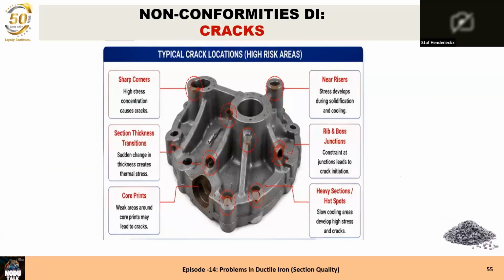Again, where it happens, it's sharp corners, or of course the most important area where it can happen, where the section thickness changes, and when it's a very abrupt change, it's one of the things that really happens there. Core prints are also many times prone to a crack. Near a riser, then you have a hot crack. Rib junctions and bosses are a matter of difference in section sizes. And in heavy sections, you can have hot spots during the cooling. Now, I must say that cracks are in ductile iron much less frequent than in steel or gray iron.